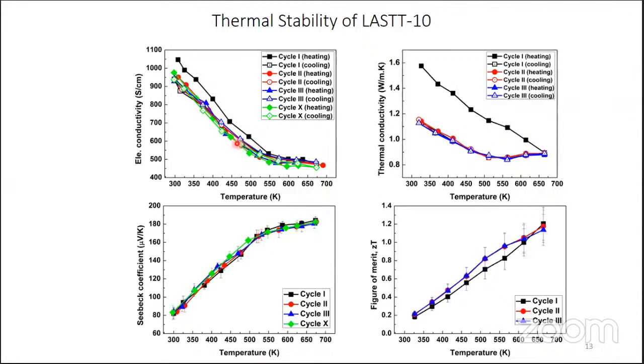So after 10 times, from the second cycle onwards, you can see that all of these are almost comparable. Seebeck is comparable, and electrical conductivity is also comparable. But in the first cycle alone, for both electrical conductivity and thermal conductivity, there is a difference between heating and cooling. So it means something in the as-prepared condition, after melting, processing and making a pellet, and then measuring for the first time, if you take this data only by heating, this cycle alone, you will get some data.